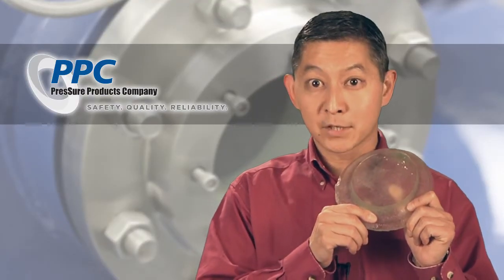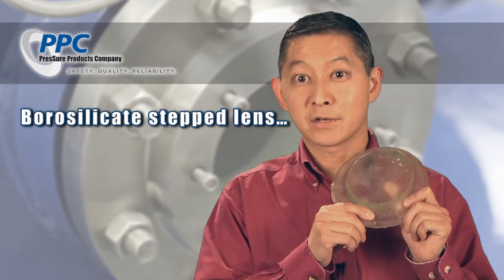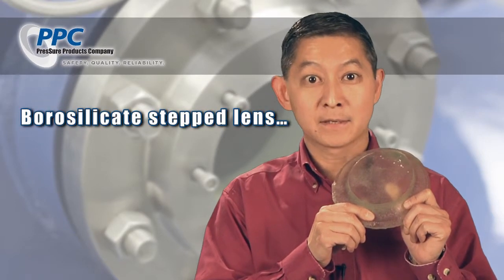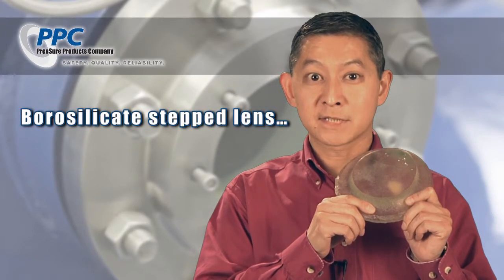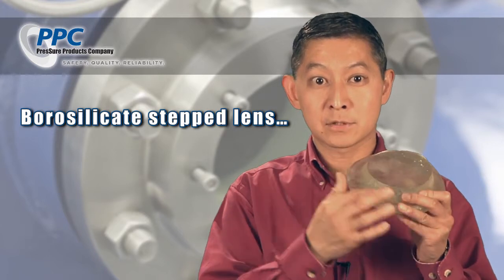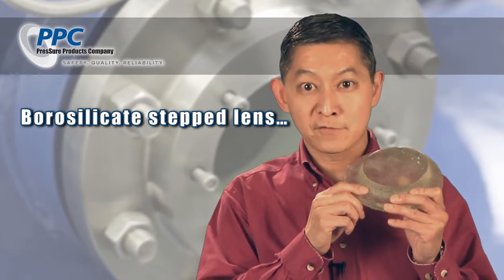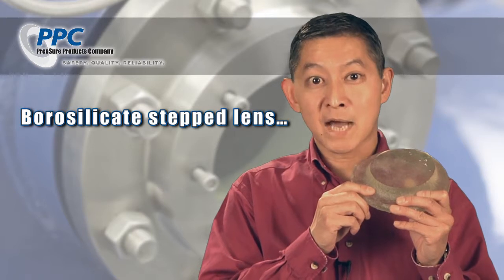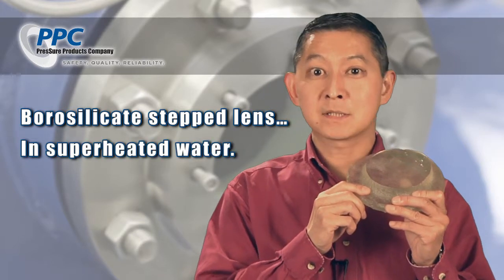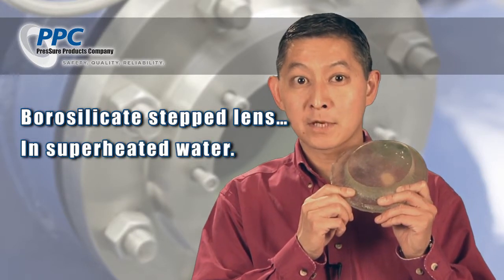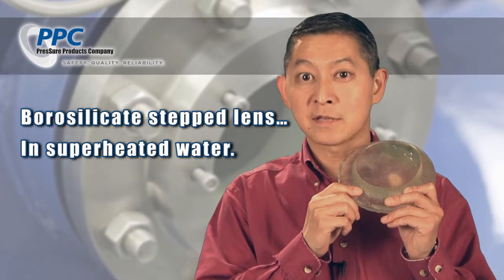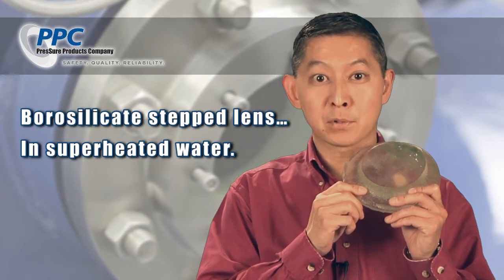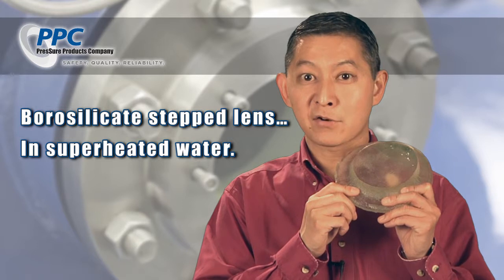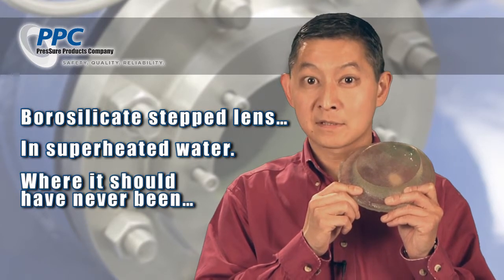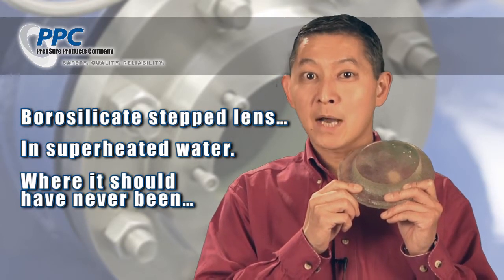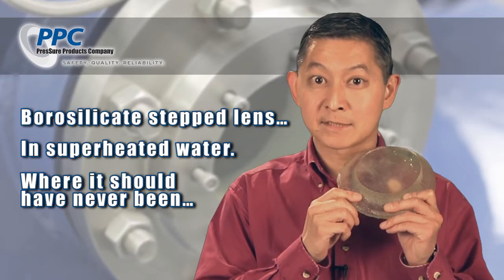This is a borosilicate side window, and it's easy to tell that a huge amount of glass has been etched away. Now this piece started out as a stepped lens, so some glass around the edges had been machined away during manufacture. But obviously, a lot of glass had been lost. This piece of glass was in superheated water application, so the corrosive agent that ate away all of this glass was just pure water. And this happened in a matter of months, not years. This is not a small effect. So, how did water eat away all this glass?